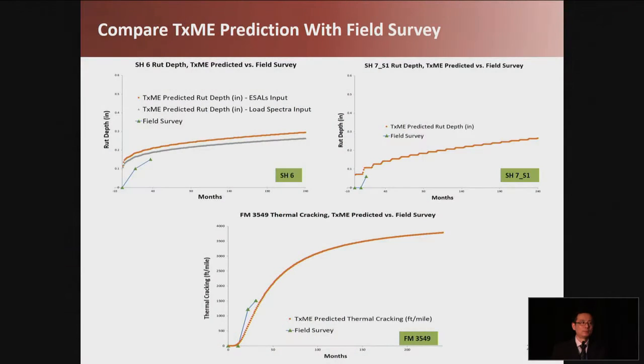So here, the green line is the measurements from the field survey. We do the survey on average twice a year, once in the summer and once in the winter, to get the survey results. And the red line is our TexasME prediction. For SH6, we have both: using the ESALs and using the load spectra information from the portable WIM data. And this is the comparison for rut depths for SH7 section 1. And this is for FM 3549 for the thermal cracking. So basically it matches pretty well.